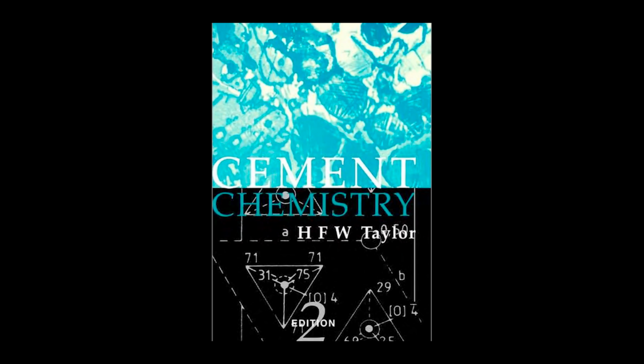And its alkali chemistry is key for mitigating ASR, right? Crucially, yes. The alkali cations that are released from fly ash are less effective at raising the pore solution pH compared to the alkalis released directly from cement. And since ASR is so dependent on high hydroxide concentration, PFA substitution is a primary strategy for mitigating ASR risk.